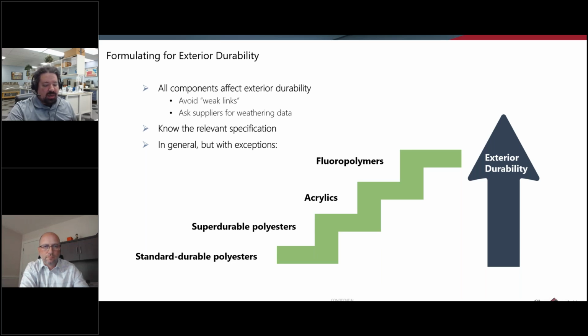And at the higher end of the scale here, we've got fluoropolymers, which is where, they're pretty much a requirement for 2605 for Qualicoat Class 3. A properly formulated fluoropolymer will overshoot the 10-year Florida requirement by quite a bit. These are more like 25-year coatings.